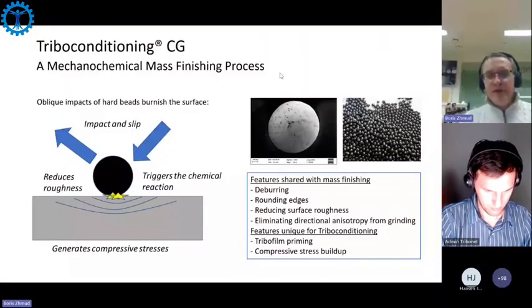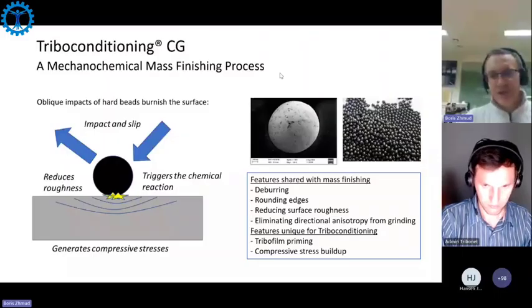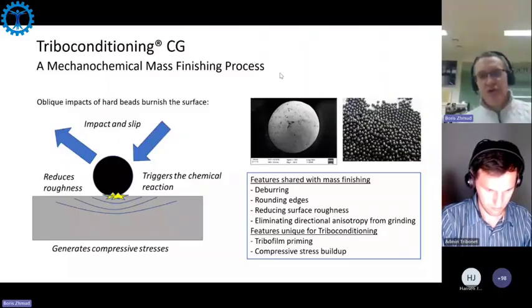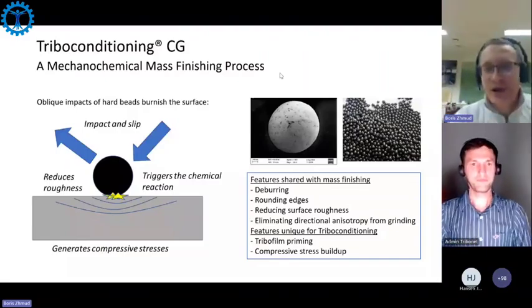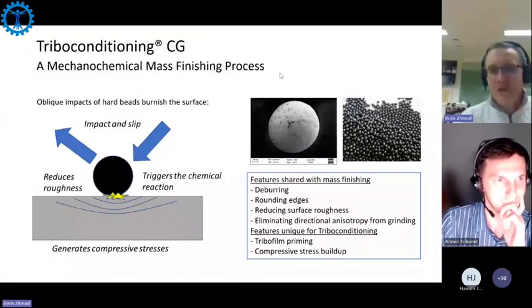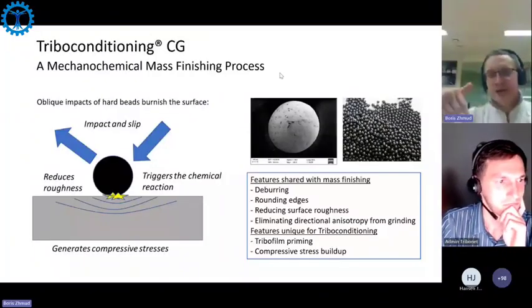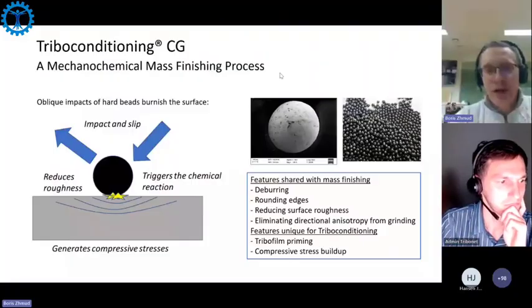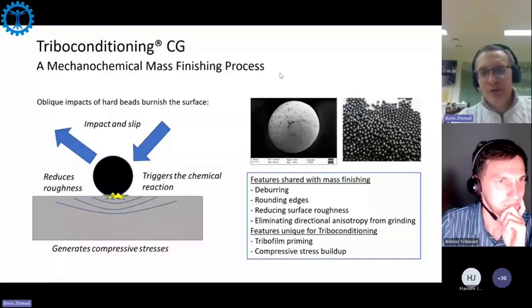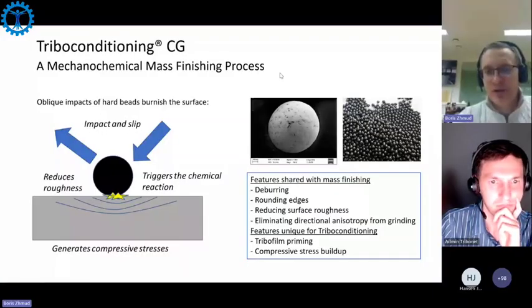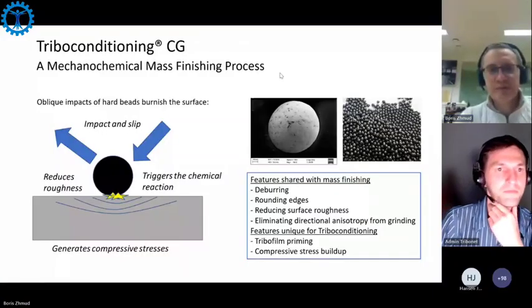The process itself, it basically looks to some extent like shot peening, but except that we don't have shots and they fly at lower velocity. So basically, surface is bombarded by small balls, 1 to 3 millimeter ceramic balls, which produce, I would say, some impact, some burnishing effect, and they also trigger tribochemical reaction to deposit tribofilm on the surface of the component.